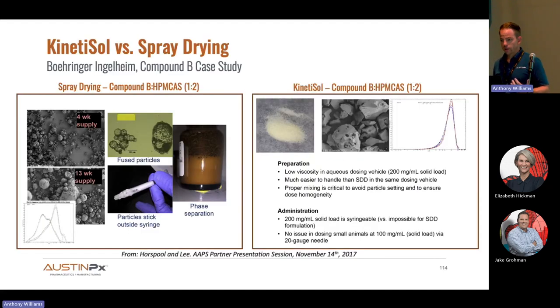So early on in our history, we had a fairly extensive collaboration with Boehringer Ingelheim in Connecticut. And they originally came to us with the issue illustrated on the left. They were using SDDs in preclinical studies, and they were having issues with respect to suspendability and gavageability of spray-dried dispersions, batch-to-batch variability. The dose in their tox studies was being limited by what could be administered from suspension with an SDD. And as they got into chronic tox studies and the demands for drug product approached the 100 kilo scale, they were having issues with supply chain and budget.